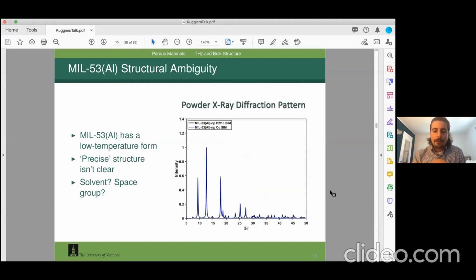The powder X-ray diffraction patterns for these two cases are identical, because it's such a subtle change in the structure, whether that water molecule is symmetry independent or not. So if you look, the two structures are overlaid here. They're identical. You can't make the difference out using X-ray diffraction.